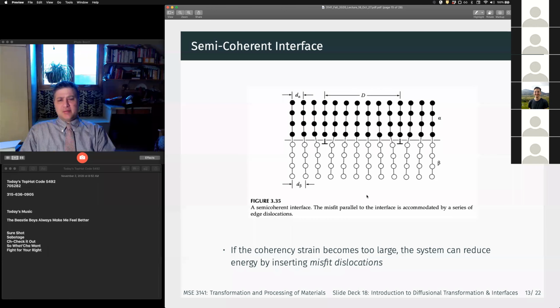All right, so a really important concept, right, that applies to much more than just the types of phase transformations that we're talking about here. And these dislocations that pop in are called misfit dislocations, right? And they serve to reduce the overall strain. So you can see now that the atoms at the interface are displaced much less relative to what they would be if there was a one-to-one lattice correspondence.